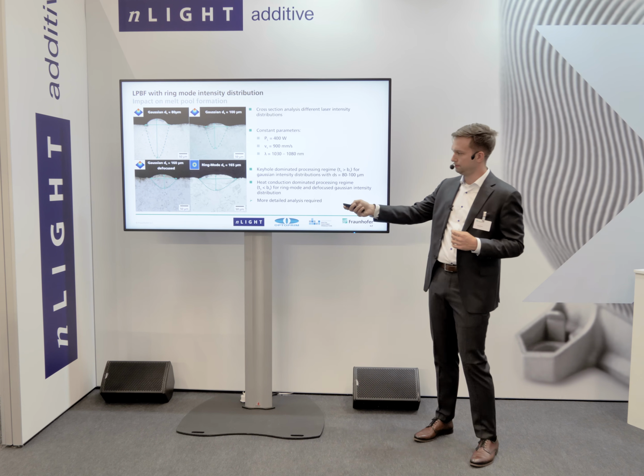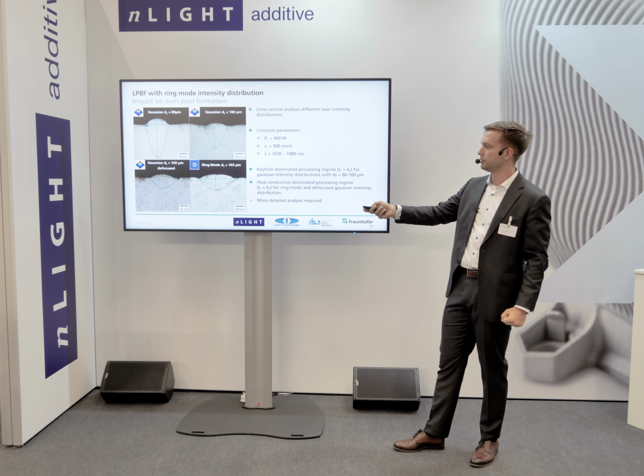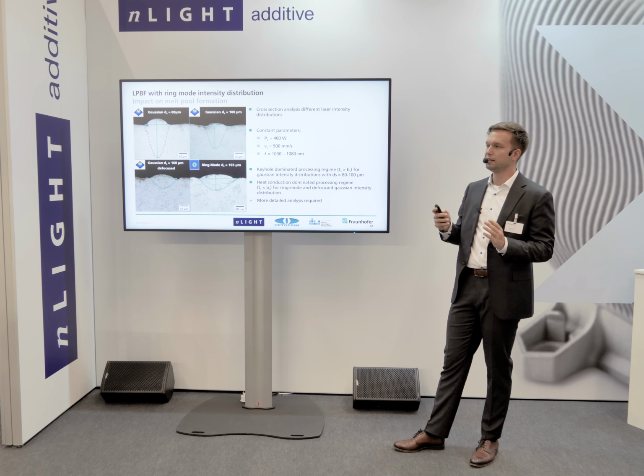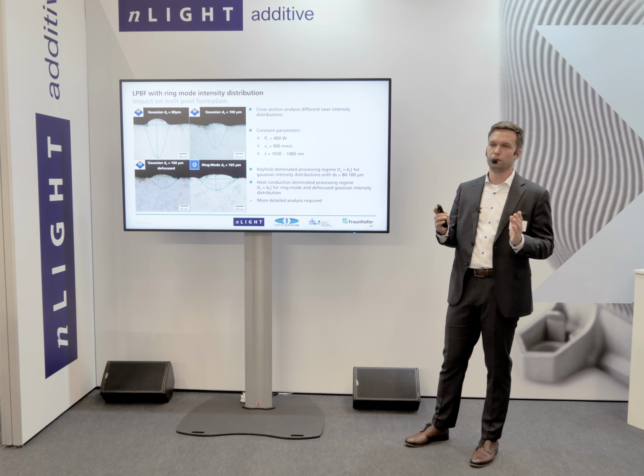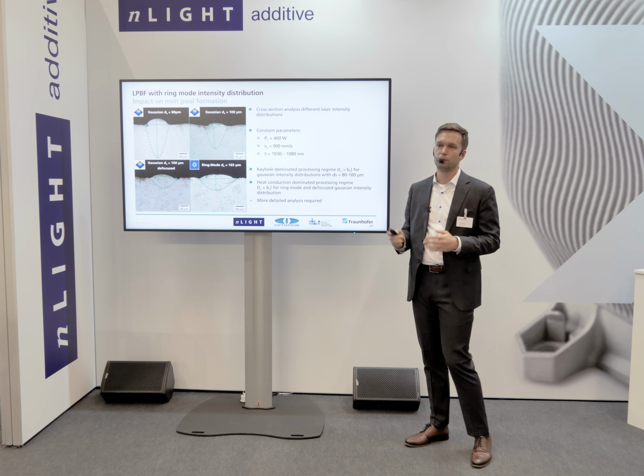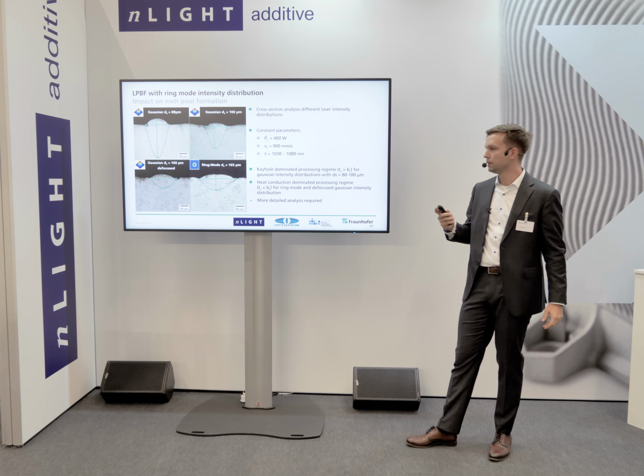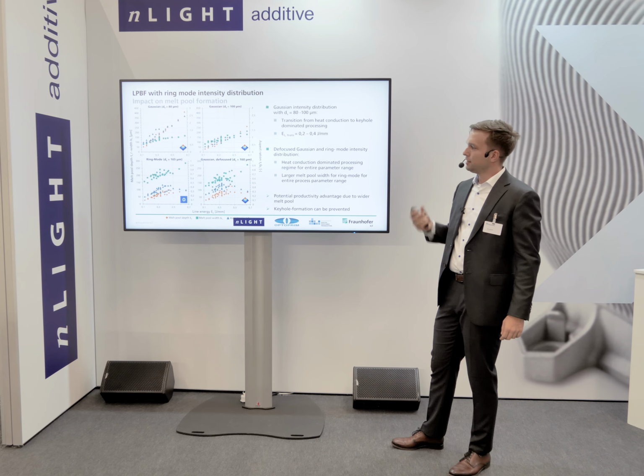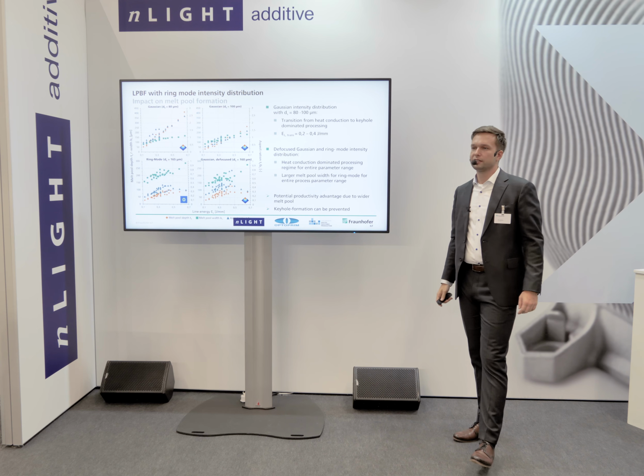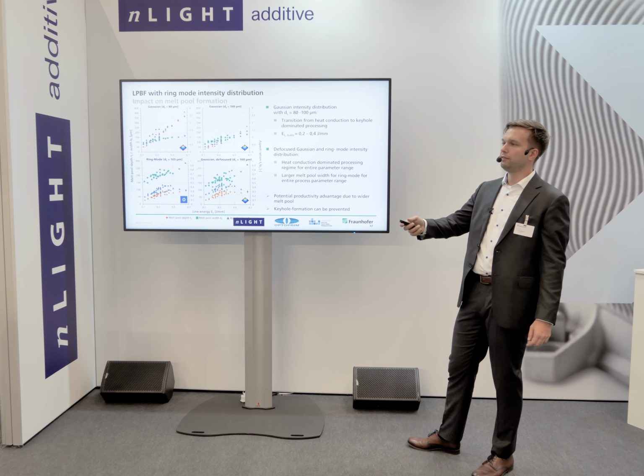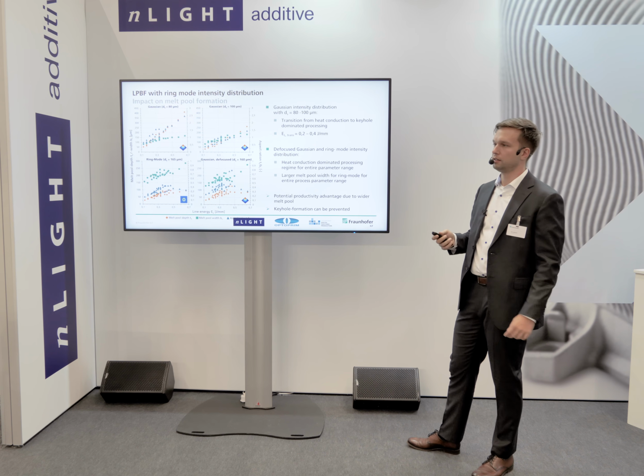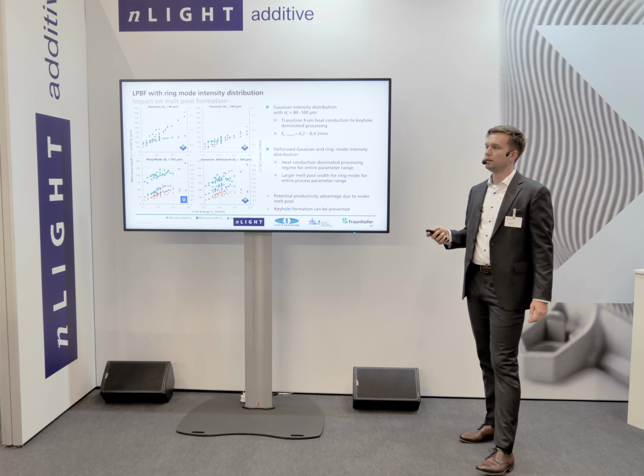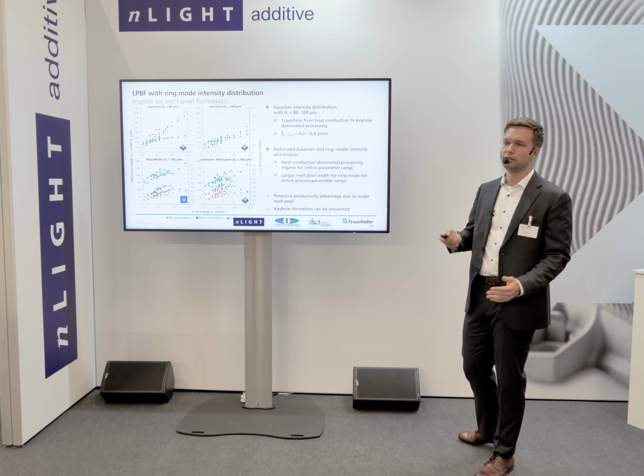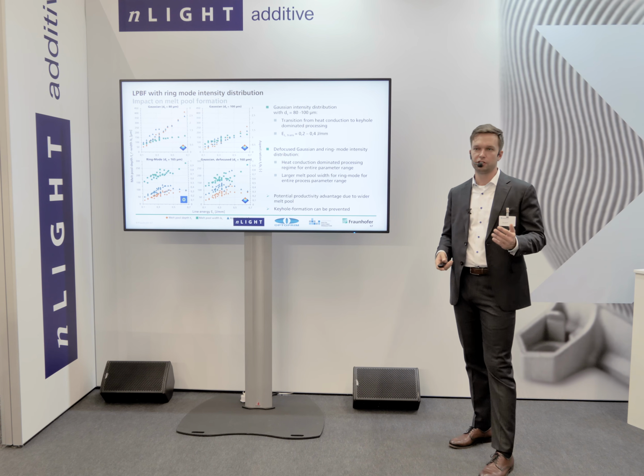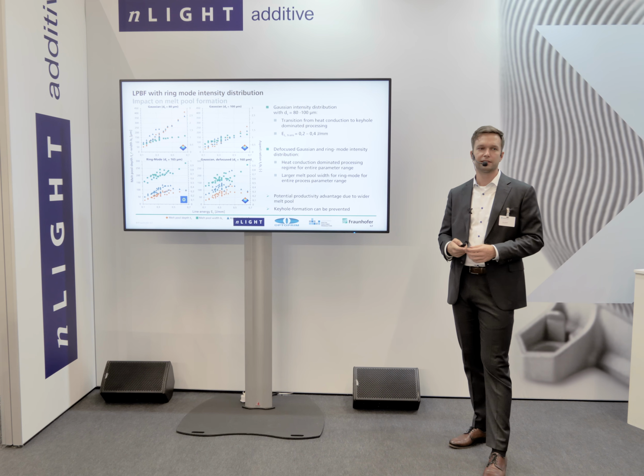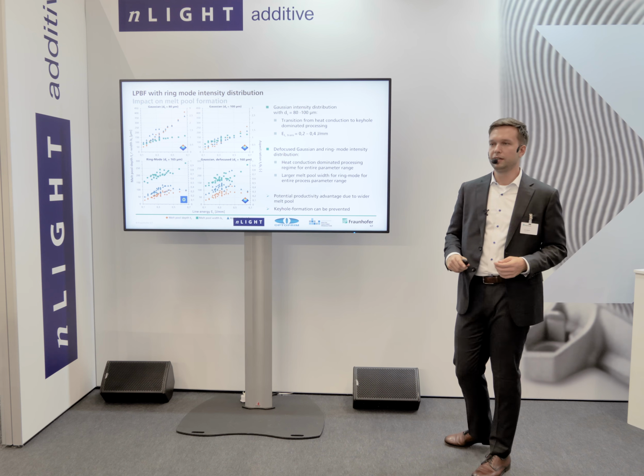But when you compare the Gaussian and the ring mode side by side, you will realize that the tendency is that the ring mode profile yields a wider melt pool, which could be beneficial in terms of processing speed. What we then did was a more detailed comparison of the two by varying the scan speed and the laser power, and we analyzed depending on the line energy, which is basically just the ratio of laser power and scan speed, how the melt pool behaves.